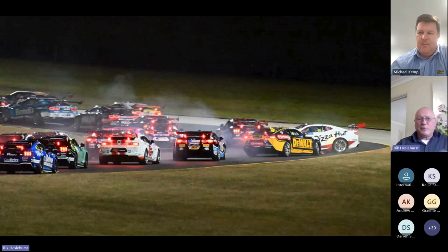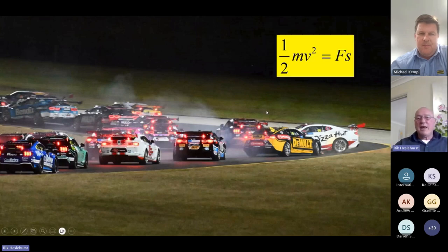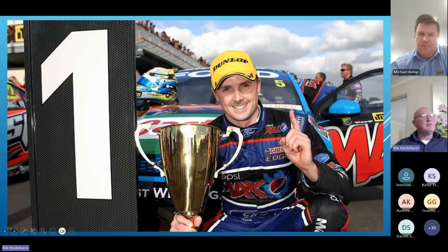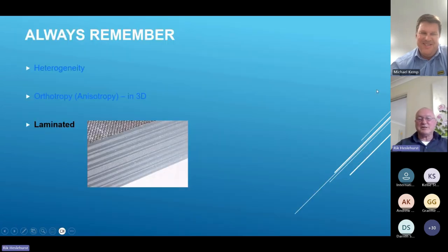Well, they weren't. I mean, we just changed the ply position. We didn't change costs. We didn't change labour. It was the same bumper bar with just ply position changes. So what was the outcome? Well, basically, I should say it's all based on energy. So a vehicle going at a certain speed pushes into a bumper bar. If you get more deflection in bending, you have less force. And so it stops you pushing you off the racing line and causing damage to your bumper bar. So Mark Winterbottom won the Drivers' Championship that year because he stayed in the top 10 positions longer than others because of his bumper bar and his racing conditions.